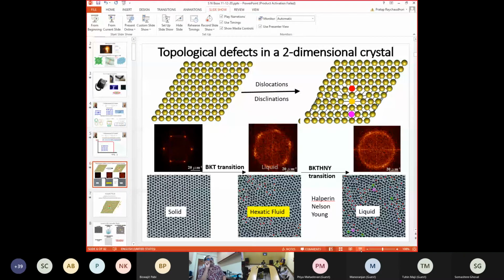As it so happens, they were only partially correct. Why? So you can see this cartoon of the crystalline solid here, hexagonal solid, and then you have here a large number of dislocations which have proliferated. These dislocations are these red-white pairs here. However, what was realized is that this state, which Kosterlitz and Thouless thought is the liquid state, is actually not a liquid. And you can see that if you look at the Fourier transform.